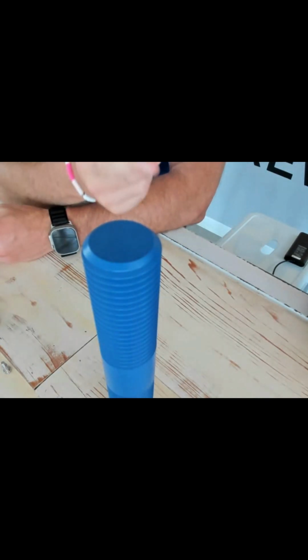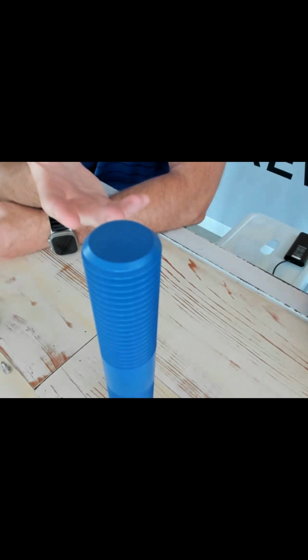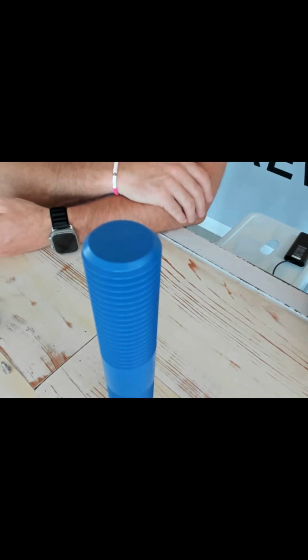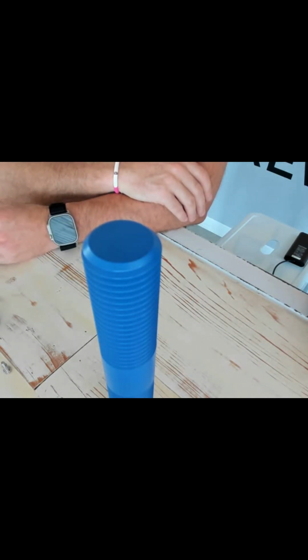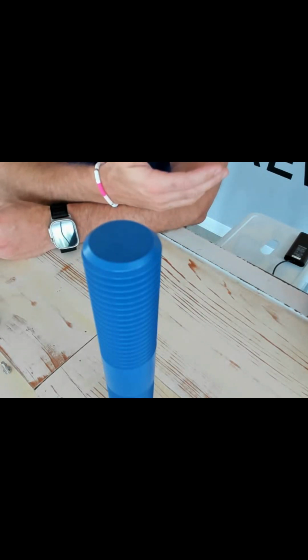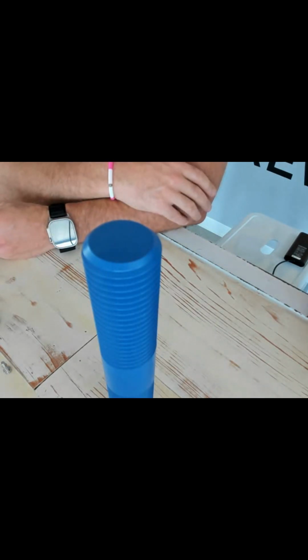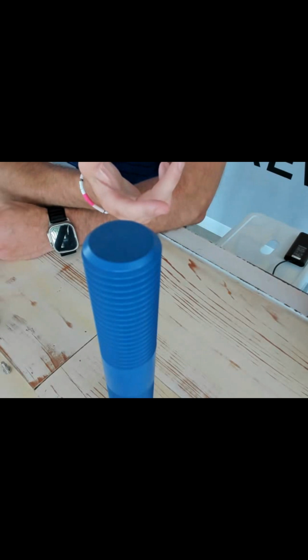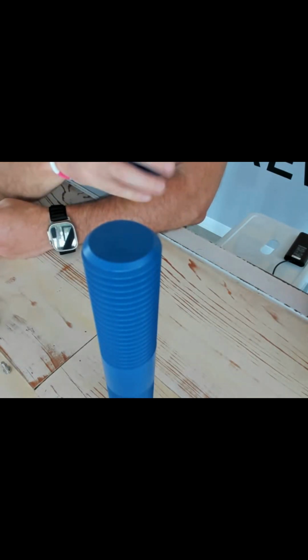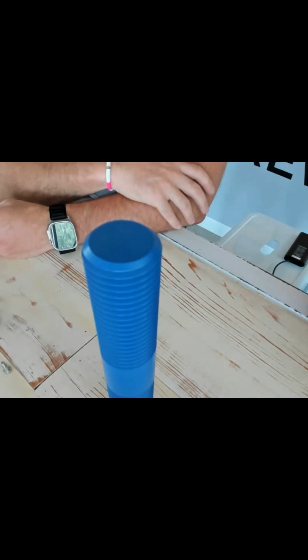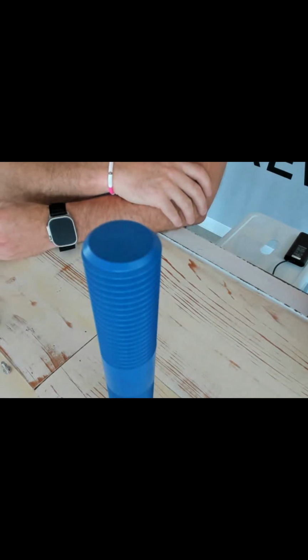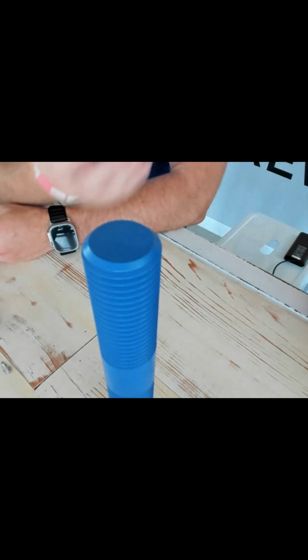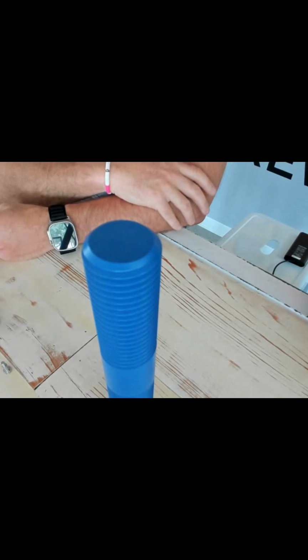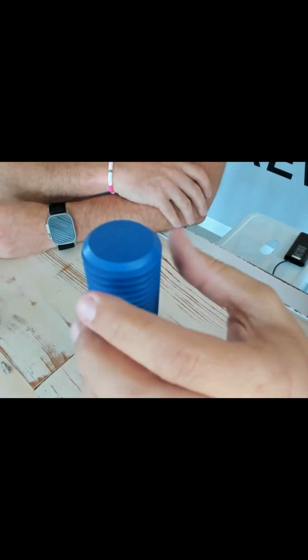And to that note too, a lot of times when you're coating something with PTFE, you're going to over tap the nuts to fit on. So typically you're taking 10 thousandths off of the nut to open it up a little bit, yep, and then coating the nut, and then it allows for that thickness of the coating to spin on. So I know there's some applications that don't allow. I know API, they don't allow over tapping with the current. Yeah, we're talking about a very thin coating.